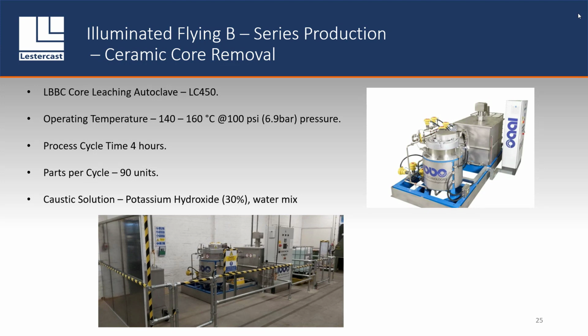So potassium hydroxide goes into this vessel here, which is where the parts are located in a basket in a configuration. And basically it gets soaked with potassium hydroxide. It agitates as well through air pressure, and then it has a water rinse and a flush. And that happens multiple times over the space of about 4 hours. In doing so, the potassium hydroxide in this particular percentage attacks the ceramic core. It doesn't damage the casting, which is obviously very important. So that's the best way, or the only way really, of practically removing that very small core with that channel through this component.